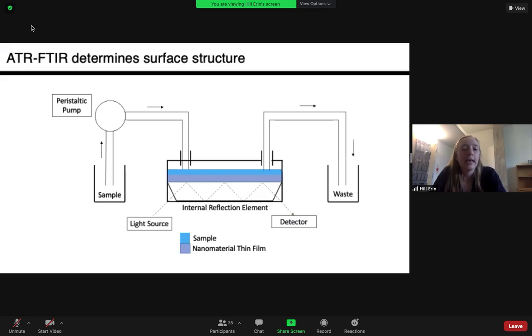So like I said, ATR-FTIR was used to analyze the lab samples. This is a surface-sensitive technique, which is important for our work, and it monitors surface changes to nanoparticles in water, and it allowed us to determine the coordination of phosphate onto LCO. The sample passes up through this peristaltic pump and down onto the nanothin film material. The nanoparticles were spread across a zinc selenide crystal, and phosphate solution ran across the crystal.